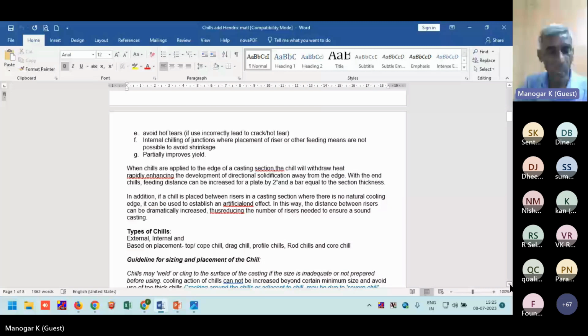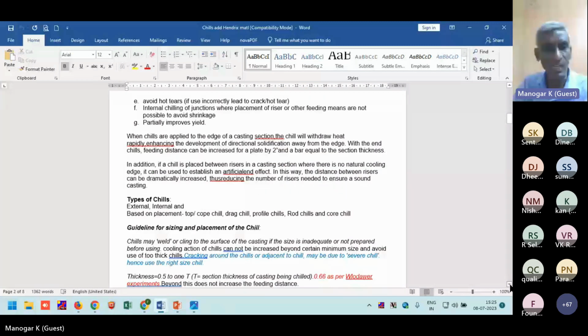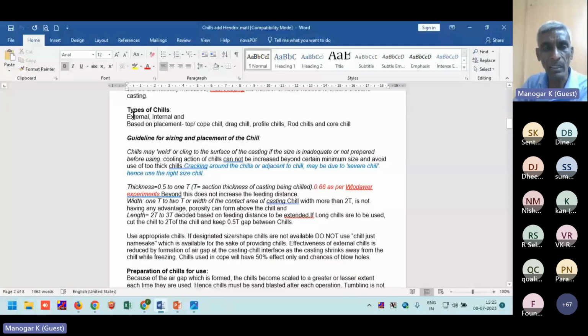Types of chills we use: external chills, internal chills, and based on that, top or cope chill, drag chill, profile chills, rod chills, like that. The thickness of the chills should be 0.5 to 1 times the thickness of the casting. As per Wlodawer, 0.66 is effectively working. And the width of the chill should be 2 times T, and length can be up to 3 to 4 times, depending upon the feeding distance you are looking for.